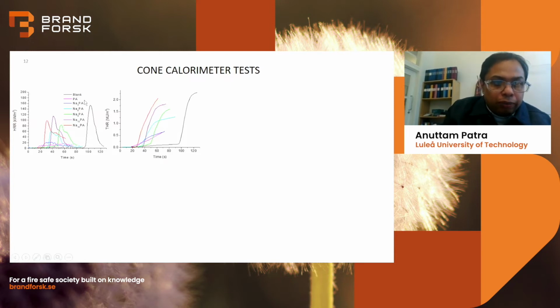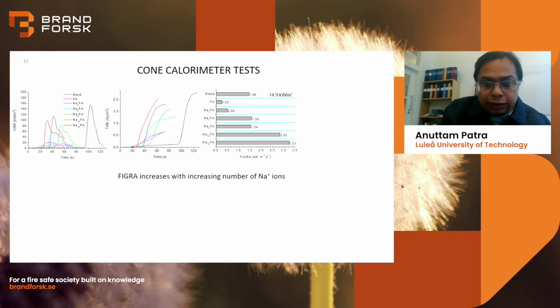We also prepared PA, Na3Pa, of course Na6Pa, 9, 12, and 16. And it was interesting to find that for PA and Na3Pa, the heat release rate, HRR, is much lower. And if we look at the FIGRA index, which is the maximum HRR for one sample divided by the time it took to reach that maximum, we see the FIGRA index increase almost linearly with increasing number of sodium ions.